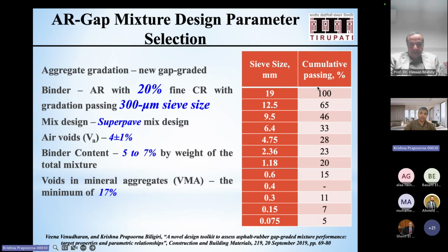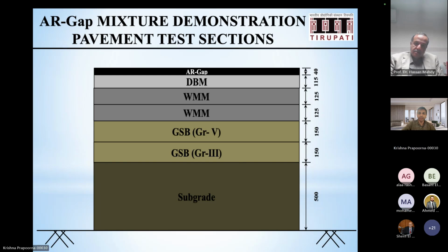Okay, you can come up with these designs based on the balanced mix design as well, coming up with performance criteria, including the rutting and cracking with respect to the aggregate gradation, binder concepts, volumetrics, and many other things. Okay, so this is a published document in the Construction and Building Materials, very highly impacted journal there. Okay, so we also did a demonstration section, an actual pavement section, where we just paved the surface wearing course 40 millimeter. It's about 1 to 1.1 inch, 1.2 inches there.